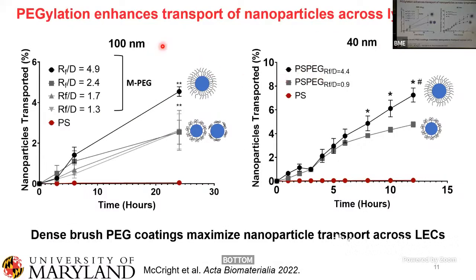So we did this for both 100 nanometer particles. We know those are sizes that really effectively get into lymphatic vessels based on the literature. And we found, really interestingly, that in both cases, the densely PEGylated particles actually maximize the transport across lymphatic endothelial cells in vitro. And that was true for both our 100 nanometer particles as well as our 40 nanometer particles. Not to say that PEG wasn't helpful. Some PEG was definitely helpful. It just wasn't quite as good as when you have a dense layer of PEG.